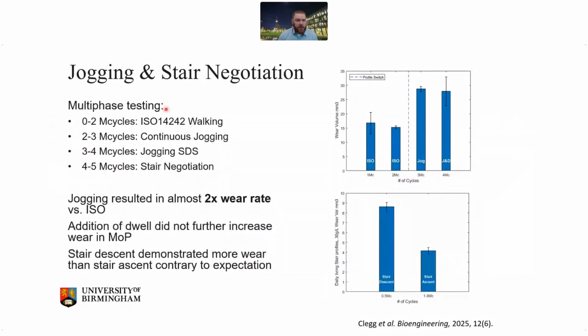And one of the things we did, so I said we looked at jogging and also stair negotiation. We ran one multi-phase test where we started initially just with the ISO profile, and then we switched to a jogging profile, which was run continuously, and then switched to jog and dwell. The jog profile doubled the wear rate compared to the ISO profile over the first 2 million cycles. The dwell didn't increase the wear rate any. We expected it did, but for the metal on polymer device, it didn't, and that may be more important for hard-on-hard bearings. But there was an increase in the variability between the samples there.